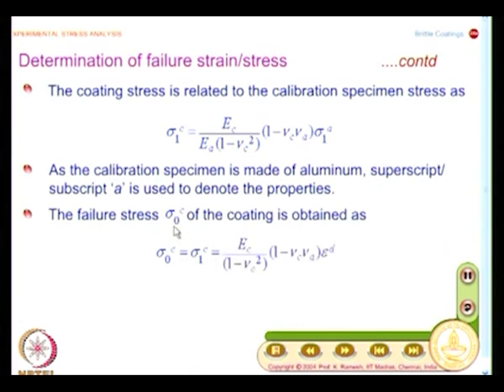Now, I put a 0 and say that this is the failure stress of the coating, and from this expression I write sigma naught c equal to E c by (1 minus nu c squared) into (1 minus nu c nu A) into epsilon d. Because I have a uniaxial stress applied, sigma 1 A divided by the Young's modulus of the aluminum gives you the strain. So, this is the strain for the formation of the first set of cracks, and I had already cautioned in the brittle coating test that the first set of cracks are the most critical ones.